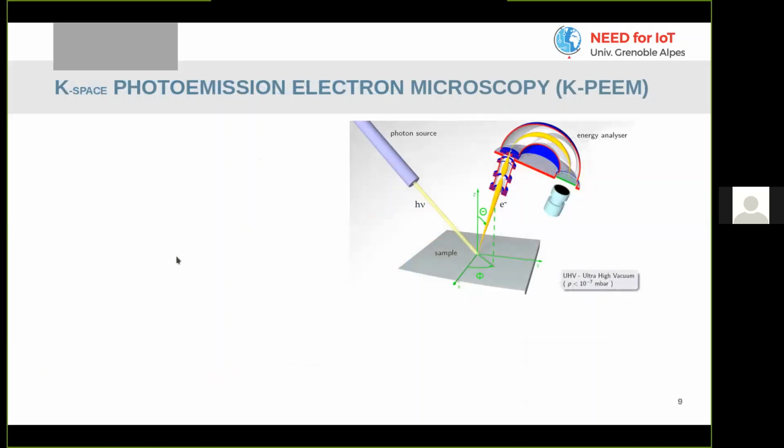Now, our means of analyzing these kind of structures is by momentum-based photoemission electron microscopy. So we're interested in getting band structures. How does this work exactly? So we have our 2D layer system, and we shine highly energetic light onto our system. Now the light is so energetic, in fact, that it's enough to lift electrons out of this system and make them photoelectrons so that they're exiting the sample eventually.